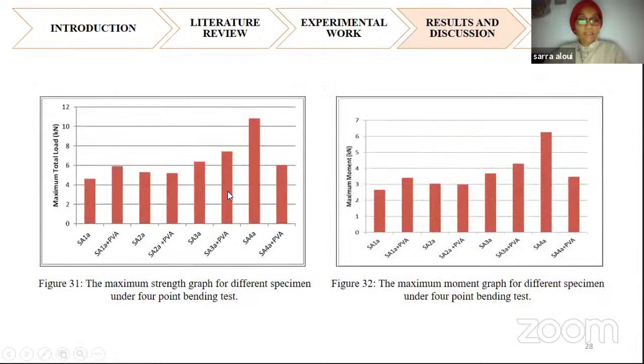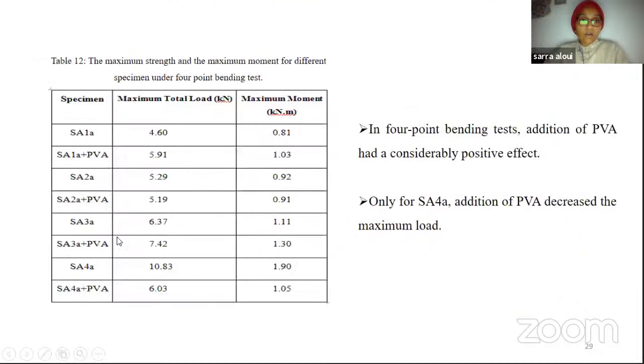If we look at this figure as well, we can see the specimen S4 has the highest maximum load and maximum moment. We can also see from the table that for this type of test, the 4-point bending test, the addition of PVA has a positive effect for all the specimens besides the SA4, because it contains more steel fibers content.